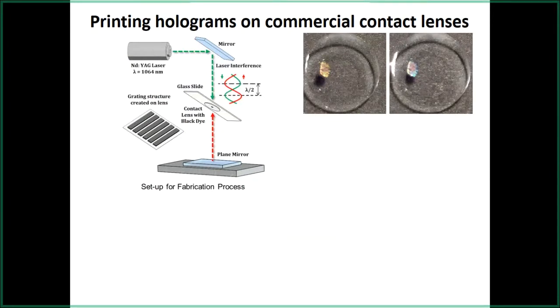Now, in most of the literature, people were making contact lenses in the lab that were mostly discs. They were made out of very hard materials, and they were very thick. They were publishing them as contact lenses, but they were not contact lenses. So using the same setup that we have, we actually produced nanostructures on commercial contact lenses. This contact lens is from Johnson & Johnson. You can get this for around 50p in England. This is a daily disposable one, which means it's the most fragile one that you can buy, so it's supposed to last you one day.